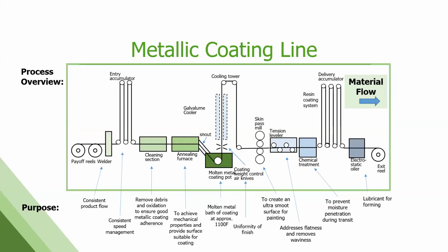For the aluminum zinc product, cleaning the surface of that steel is really, really important. So we go through a cleaning section. That's an alkaline, kind of soapy solution that cleans that surface off. Then it goes through the annealing furnace, which does 2 things. It's burning off any residuals, oxidation or debris that's on that surface. We're also heating the steel back up to recrystallize it to get the properties that we need. Grade 80, grade 50, CSA. Does it need to be hard and inflexible, or does it need to be really soft and ductile? That happens here.